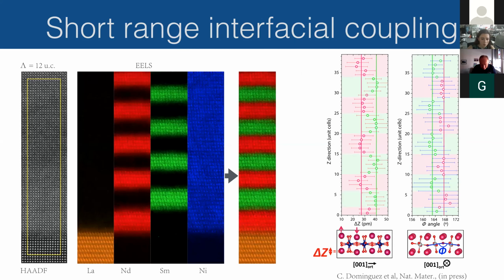So the first thing to note probably is that these are very clearly defined superlattices. There's no intermixing at the interfaces. This is showing the electron energy loss spectra for neodymium and for samarium. And you see, yeah, you go from one material to the other with no intermixing. Here on the right, we are showing two different structural parameters. The delta Z is somehow a measure of the level of distortion. It's just the cation shifts. And here phi, of course, is the nickel-oxygen-nickel bond angle that we know is super important and determines the metal insulator transition in bulk. But in both cases, we don't see one parameter that's constant over the whole structure.